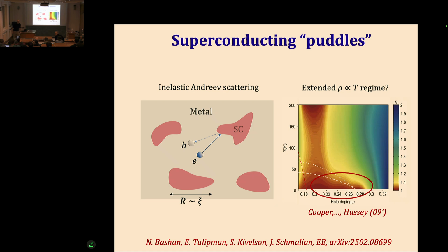So, if I understand the plot correctly, at 0.2 hole doping at 200 Kelvin, there's also linear T resistivity. How would you explain that? And then, if you increase the hole doping, it disappears and goes to a T squared regime. So you're asking about 20%, and what was the question again? The linear T resistivity, if I understood correctly, at higher temperatures is trivial. Well, it's only in the T to 0 limit.